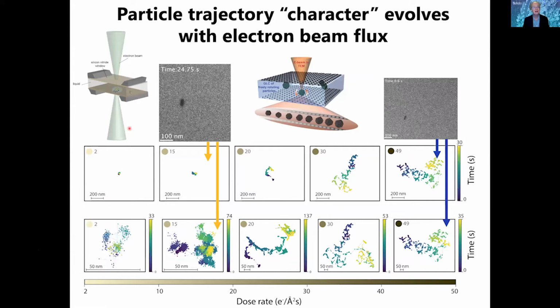There it is. So here we have a set of panels which show, for a fixed time interval, we observe a nanoparticle for 30 seconds in the electron microscope, and then we turn up the intensity of the electron beam, and you can see that it hardly moves at all on the length scale of this plot. But when we get up to the high flux of 49 electrons per angstrom squared per second, then we start to see it really moving and covering a large range.